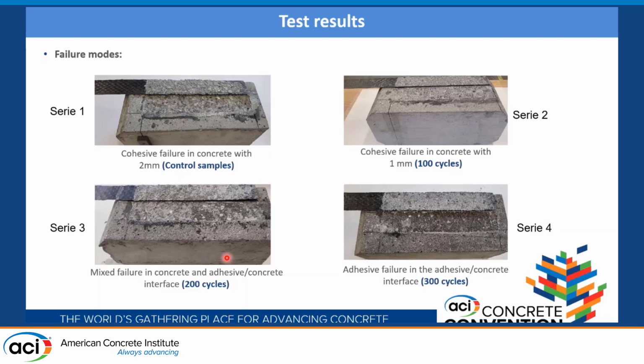The failure mode of the specimen tested after 200 freeze-thaw cycles, also series 3, was a mix between partial cohesive failure in the concrete plus a partial adhesive failure in the interface. Finally, the failure mode of the specimen tested after 300 freeze-thaw cycles, so it's series 4, was a total adhesive failure at the CFRP concrete interface.